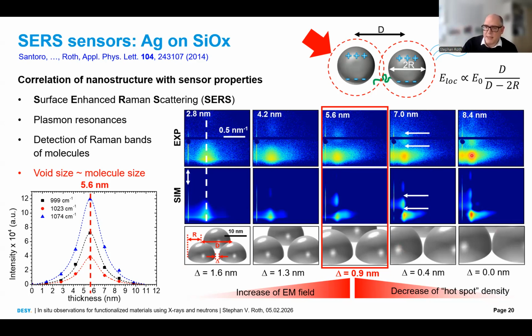And this comes back to the machine learning. Basically, what we did here is we simulate and make an eye-by-eye comparison. You can ask the students how many images they can compare per day. Certainly not 50,000. This is why we use machine learning to compare these key scattering features with our experimental data and then deduce after training. We know this is hemispherical with this distance and radius. We deduce the actual nanostructure in an automated way. Yeah, that's a perfect application for machine learning.